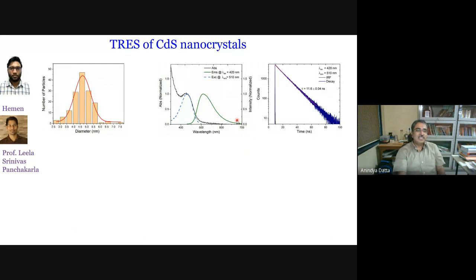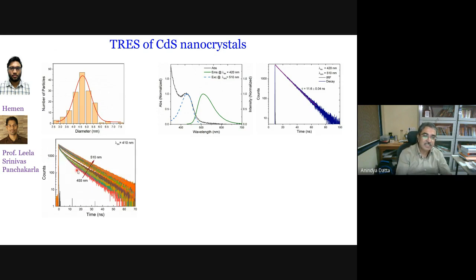More work is going on in this direction. Professor Leela Srinivas Panchakarla's group has made another kind of CdS nanocrystals capped by oleylamine. And here, Hemen has noticed something very interesting, single exponential decays with time constant of 11.6 nanosecond or so at the emission maximum. If we record the PL decays in the blue edge, we do get faster decays. Once again, the emission spectrum is broad and is dominated by trap emission.